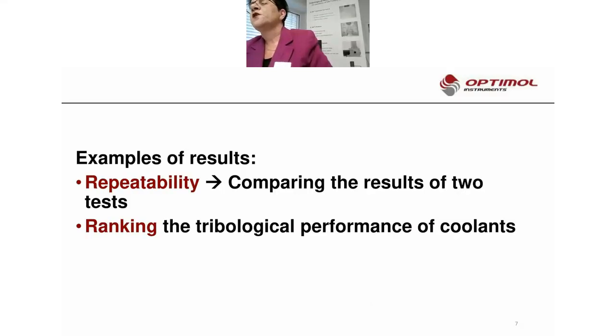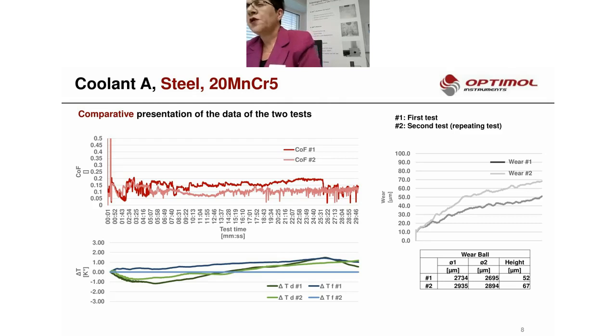I will show you a few examples of the repeatability of this test method and the ranking of the fluids. As you can see, the repeatability is very good. Here we measured the coefficient of friction for Coolant A, and the materials were steel and 20MnCr5. The wear volume could also be measured online, and we have seen that the online measurement correlated very nicely with the measurement under the microscope afterwards. The temperature development we don't concentrate on, because it was only 1 to 2 degrees Celsius, which is obvious.